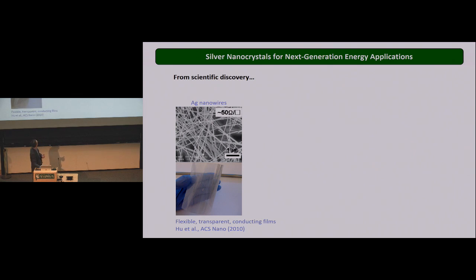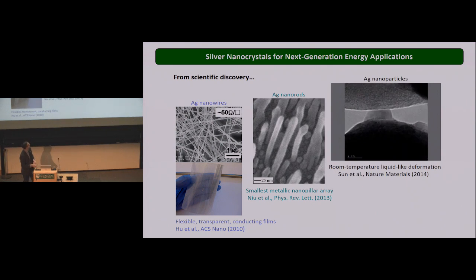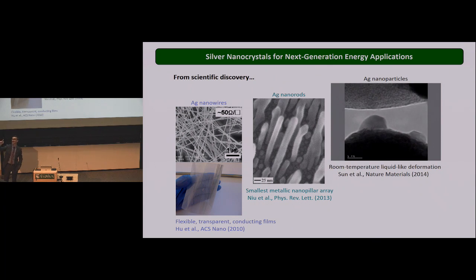And it's not my work. This is the work here. See, that video shows it in particular. See this one, yeah. And so it looks like it, but it's not. In reality, what happened is the particle remains crystalline, but the surface is turning into a melting layer. You're attributing this behavior to some kind of surface defect. Yes. Combined with the dislocation. No, so in this case, there's no dislocation. Yeah, but in my case, when the diameter is larger, yes, the dislocation will initiate the surface diffusion.